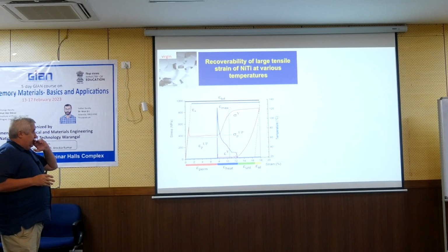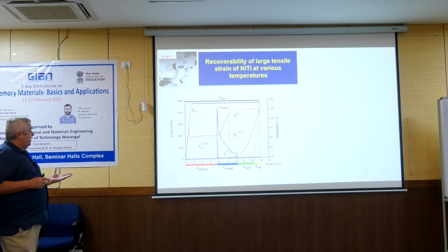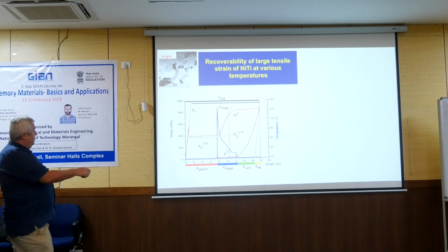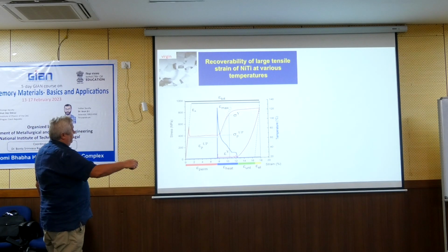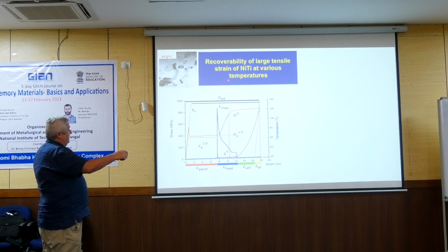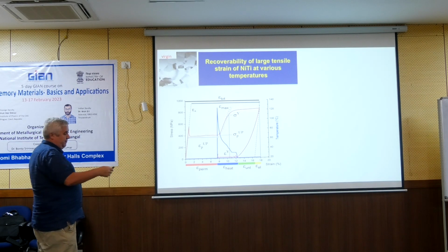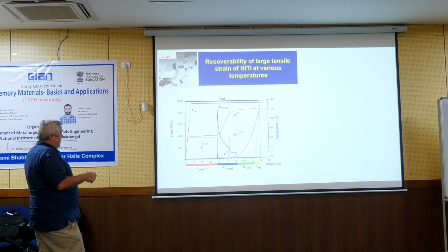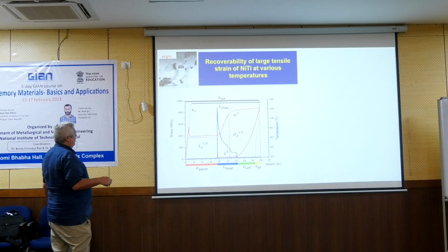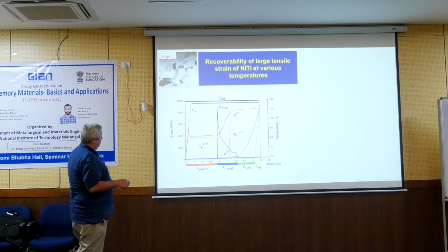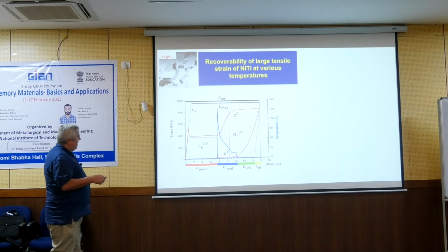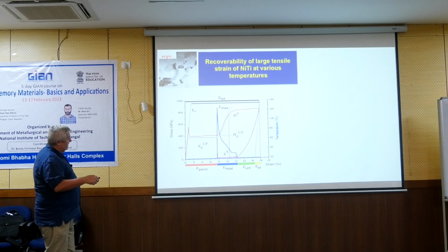But then there was a question about how the wire differs further up to the fracture, because some of the wires fractured at 13%, but some wires deform up to 50%. So we made similar experiments. Again, the Chinese girl did it. We agreed on 3 sets of experiments. So this was the third one, where we loaded up to some maximum strain, unloaded, heated. So the experiments went up to 20, 30, 50. In this way, we check the unrecovered strain and we look into the microstructure.